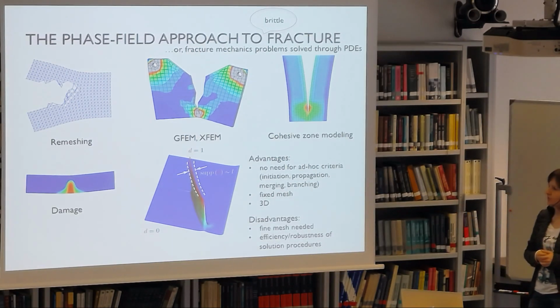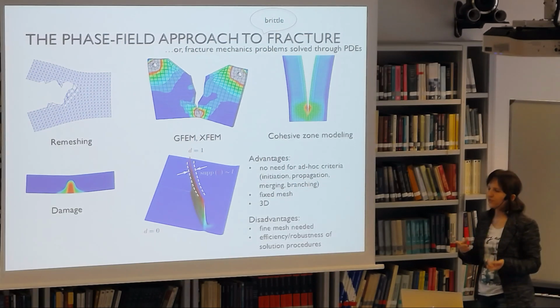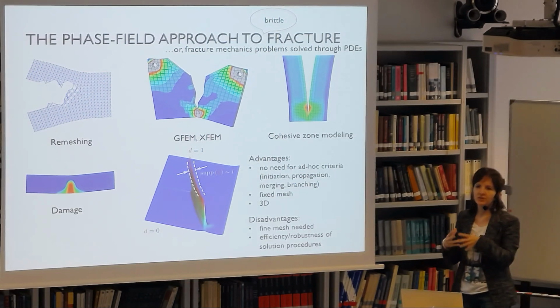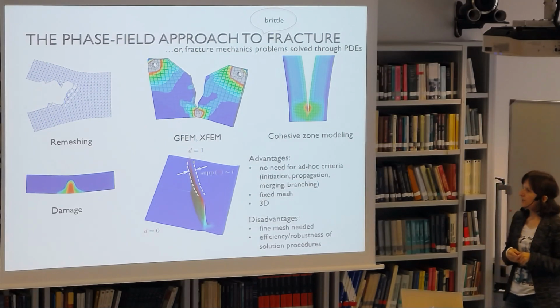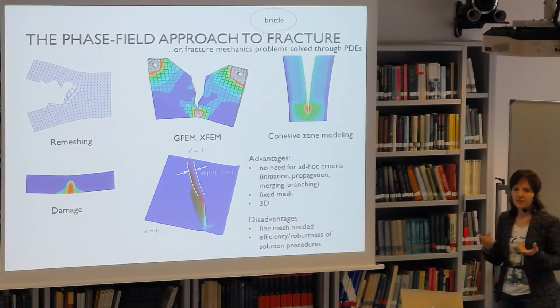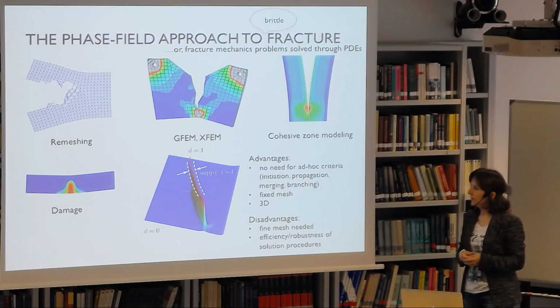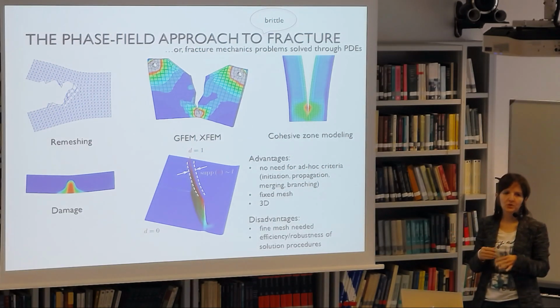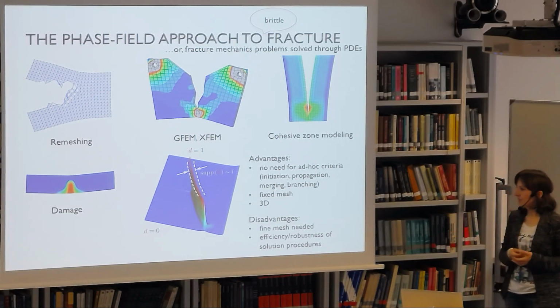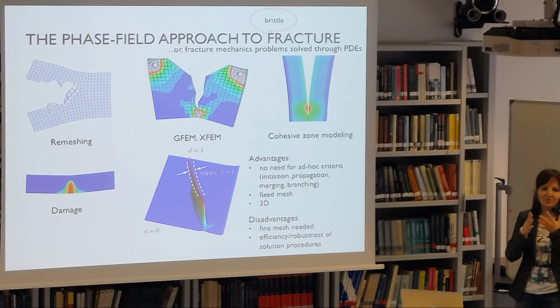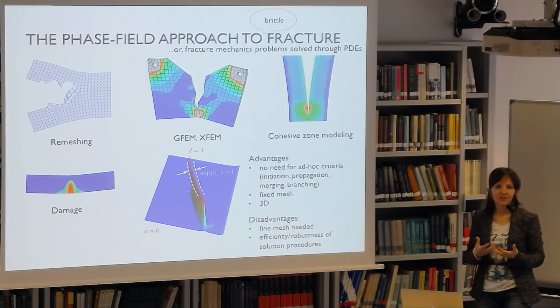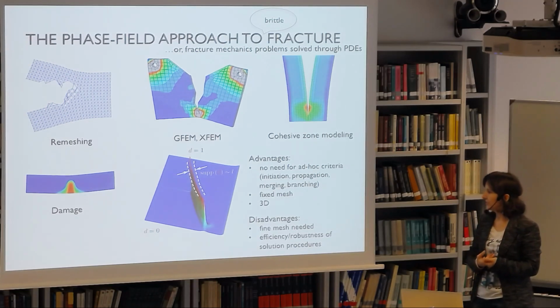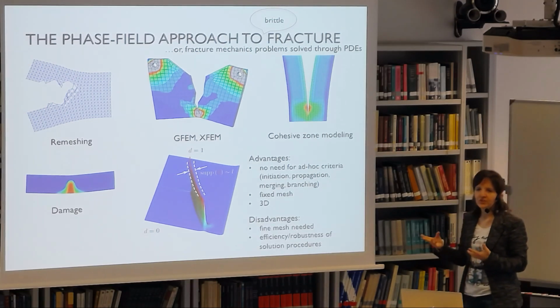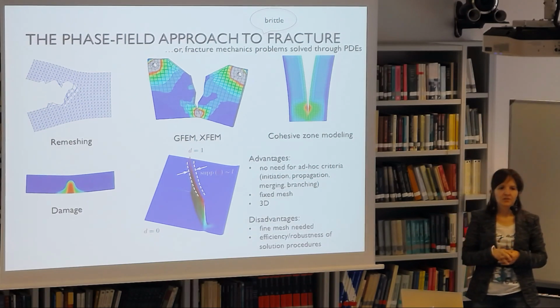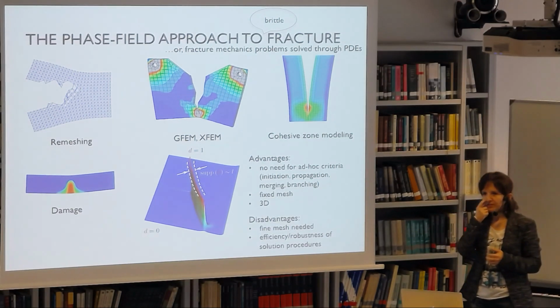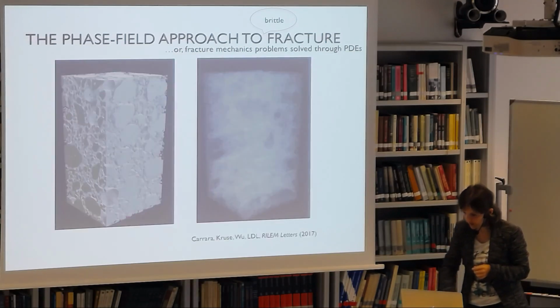And you can do this on a fixed mesh. Of course, this is not really very efficient. You would like to refine where the phase field is evolving, but theoretically you can do this also if you want on a fixed mesh. You can do it in 3D in a straightforward fashion. And the disadvantages is, of course, that you have this steep variation of the phase field, so you need a very fine mesh, at least there where the phase field is evolving. And solution procedures still need some care because of the non-convexity of the functional, which may lead to some problems.